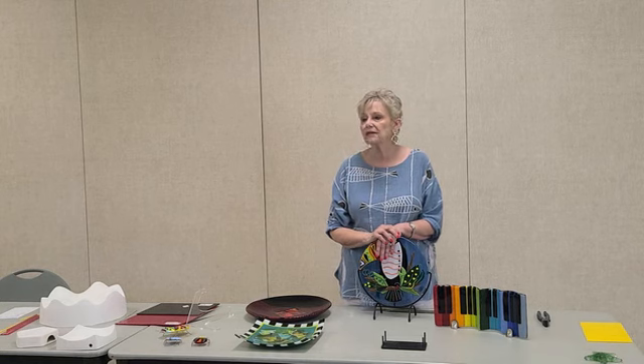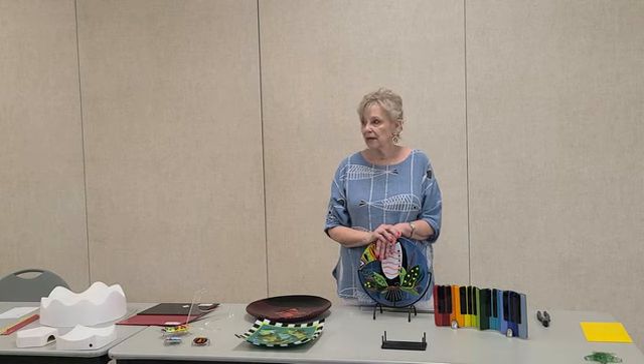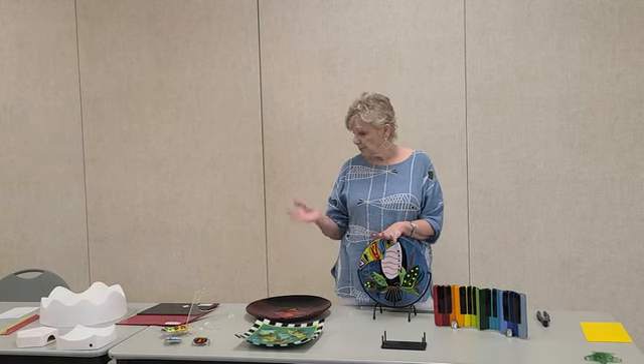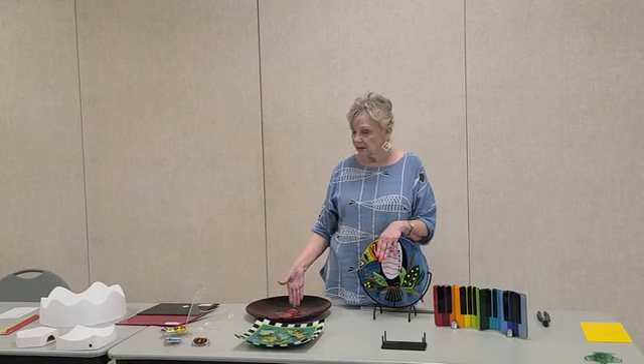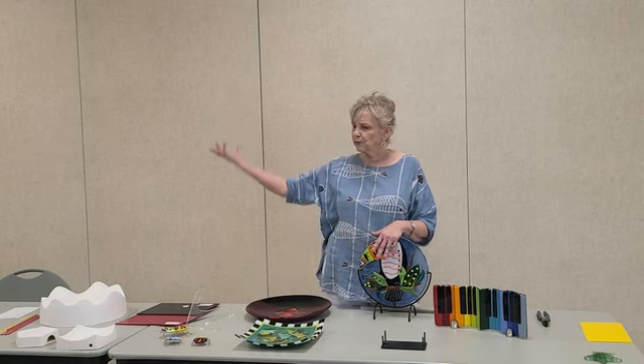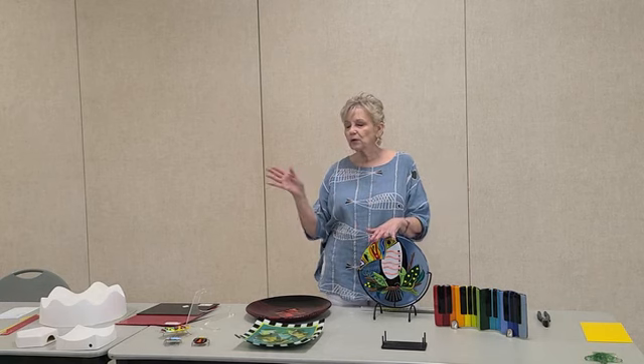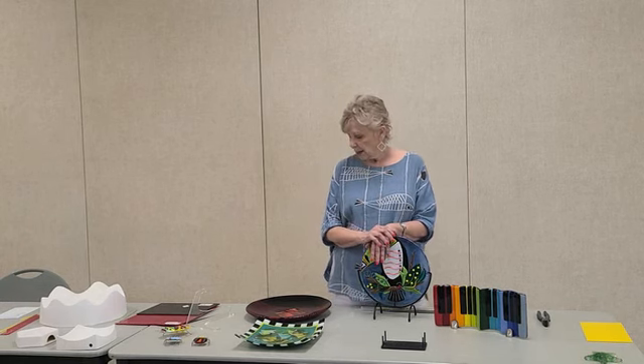There are a few colors that the other one makes that I have bought a few pieces of, but I keep them way separate. If you mistake this piece as one that's compatible with these pieces and I put that one little piece of red in there, the whole piece is ruined. It will explode almost. Not explode, like boom, but it will push away, it will have a big crack through it. You won't even make it out of the kiln. So it has to be compatible.